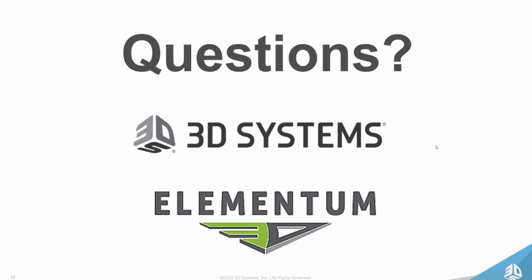Thank you. What kind of surface roughness are you seeing as built and with finishing? I could maybe just hit that for 3D Systems, and then if Jeremy or Chloe has more data from Elementum. Already with our non-optimized process that we're improving, like Dustin said, we have 8 micron Ra on vertical surfaces, which is quite good for an additive process.